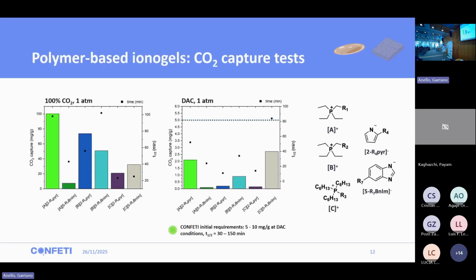For all the materials, we tested the capture capacity in different scenarios, in a 100% atmosphere of CO2 and at these conditions. As you can observe, in a 100% atmosphere of CO2, we achieve a really high capture, around 100 milligrams per gram in one of the ionic liquids. This is excellent for high concentration scenarios. However, when we move to DAC conditions, this capture drops significantly, with a maximum of 2 milligrams per gram. In our Confetti project, we have an initial requirement of about 5 to 10 milligrams per gram. So with these materials, it's really low compared with our target.